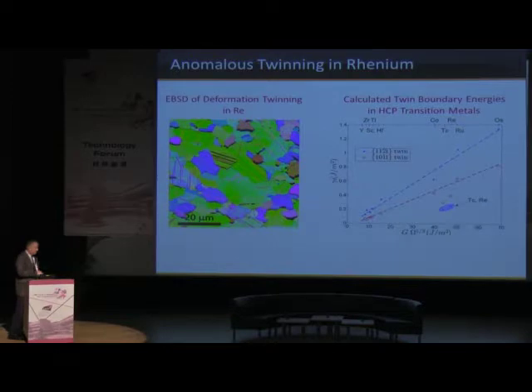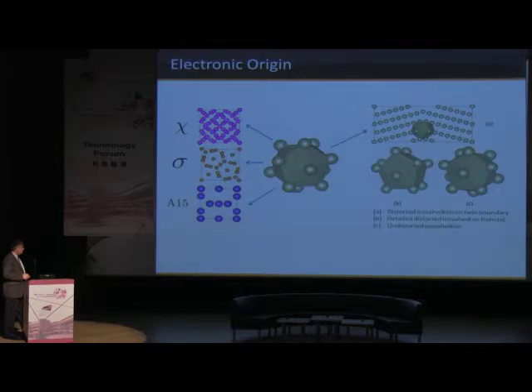So what happened here was we used high throughput computation and tried to understand a certain experimental observable, namely the HCP twin formation. We found indeed that rhenium very easily twins. But then the beauty of computation is you can start to go in and rip apart the calculations and try to understand why it so easily twins.